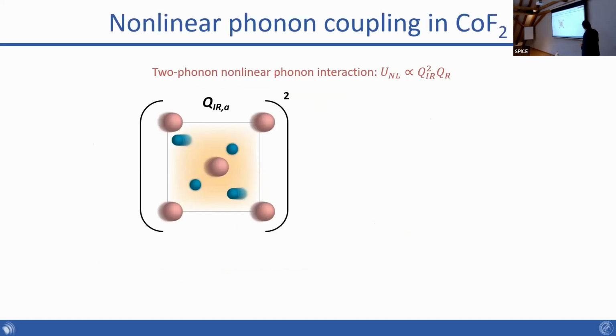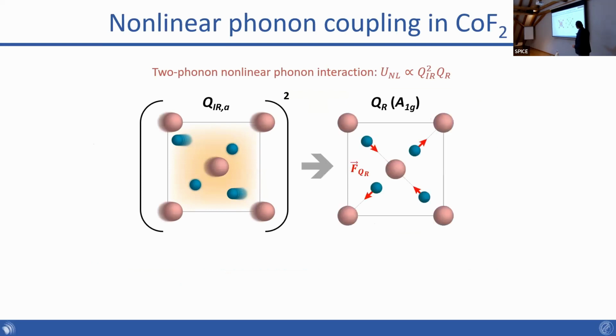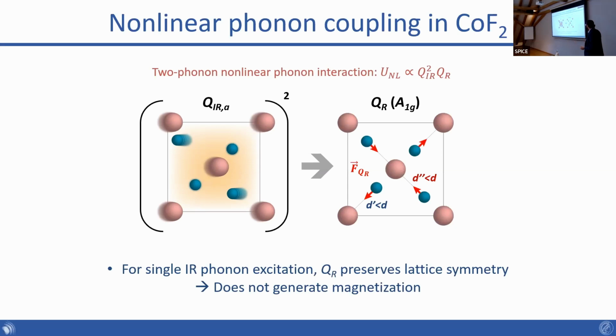If we look back at this nonlinear coupling that I talked about before between these two modes, Q_IR squared Q_R, we can try to imagine what will happen in this case. Let's say I excite a single infrared active mode in this material like this. The problem is that you can only use this mechanism to couple to fully symmetric modes. Okay, what I will couple to in this case is a Raman mode that increases or decreases the bond length in the same way on the two sublattices. So this is not going to be something that I can use to generate the magnetization.